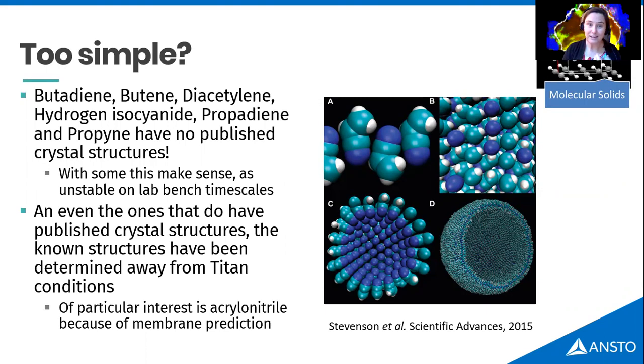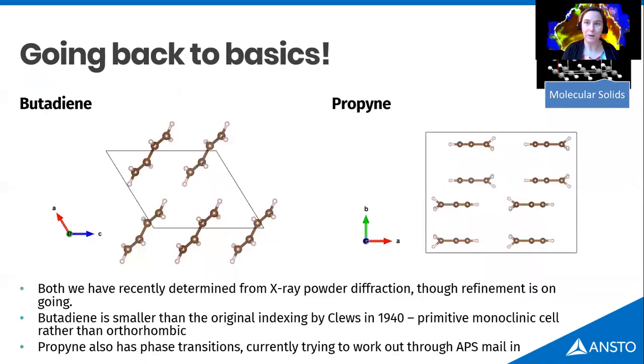And one in particular for that is acrylonitrile, and it got a lot of attention recently because a group, Stevenson et al., suggested that because it's a polar molecule, it could actually form a membrane. And then the idea was that, if this can form a membrane, maybe that's the start of a potential astrobiological system. But the interesting thing is that the structure they're basing this off was determined at 170 Kelvin. And so I'll talk a little bit about some work that we've done along the way.